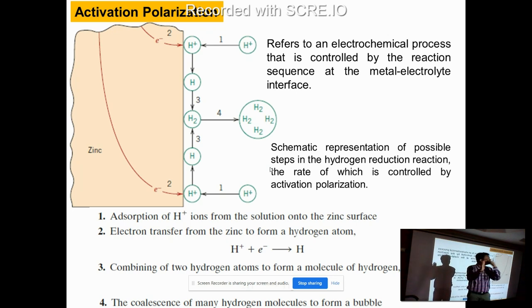Where will the electron come out? It will not come. Is it not all limiting steps? All four limiting steps. It may not react. It may not come out. If all these happen, then only the reaction will happen progressively. Clear now? Bulk diffusion has to happen. Reaction of H+ with electron has to happen. H+ has to form H2. H2 has to leave the surface, so that fresh H+ will react at the surface to form H2 again.